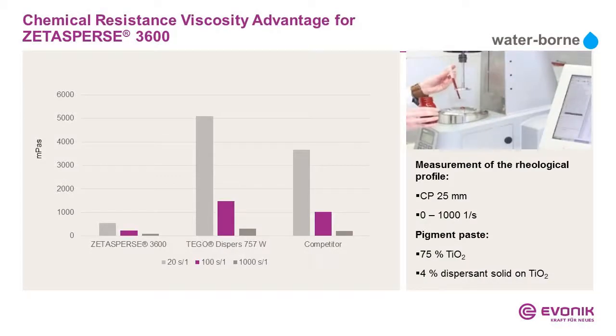You can see here the viscosity reduction. Beside the chemical resistance, also the viscosity reduction in wood coating is very important. So you can see here the viscosity reduction with titanium dioxide. So 3600 for titanium dioxide in colorants for wood coatings with very good chemical resistance. So now we switch from water to solventborne coatings. In industrial coatings, the solventborne medium is still much more important than the water.